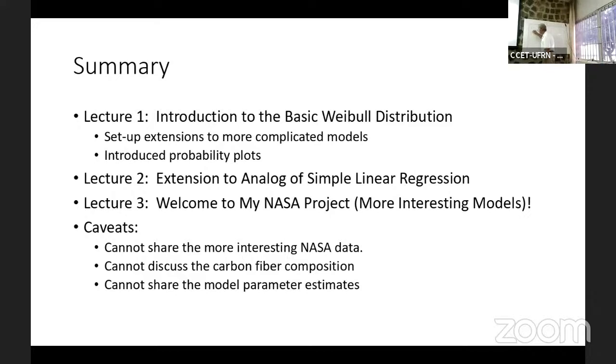This is a 2-parameter model. This is 3-parameter. The conjecture, this whole community's theory, is that the failure mechanism on ramp is exactly the same failure mechanism as on hold. Therefore, they can combine the ramp and the hold data.